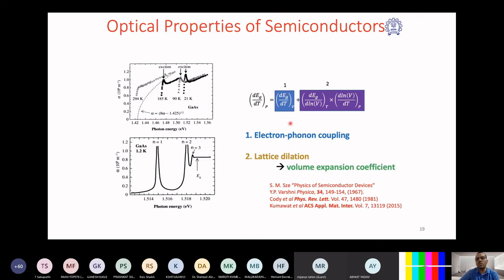One of them is lattice phonon, electron phonon interaction, which is dEg by dt, and another one is lattice dilation. The first term is always negative in energy, negative in range. So that basically reduces the band gap. As you increase the temperature, your band gap reduces. And that is what we have seen in all our classical semiconductor book knowledge and in our daily life observations.